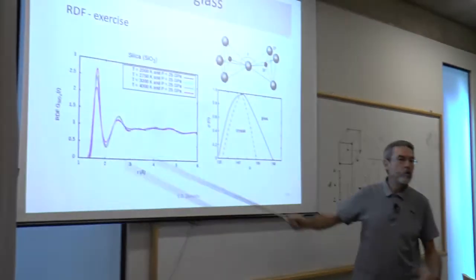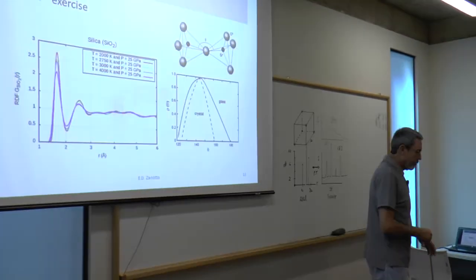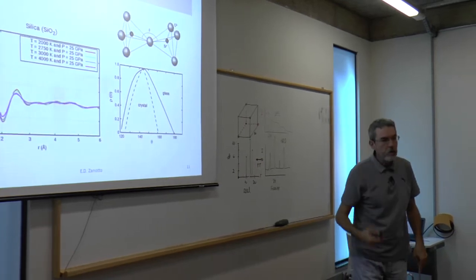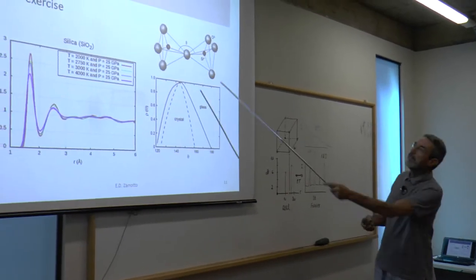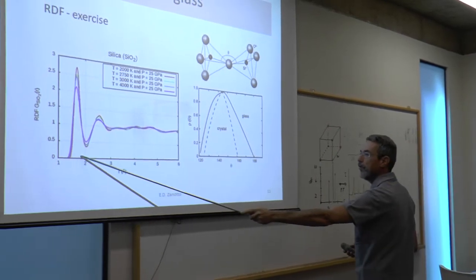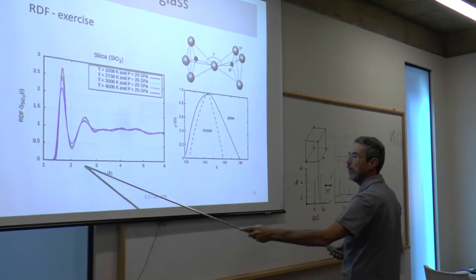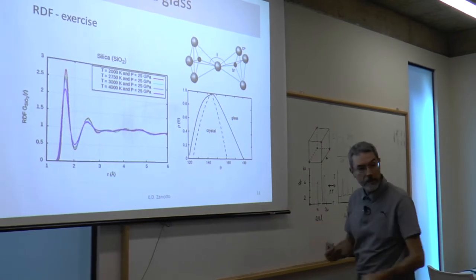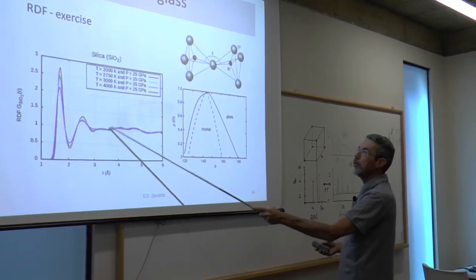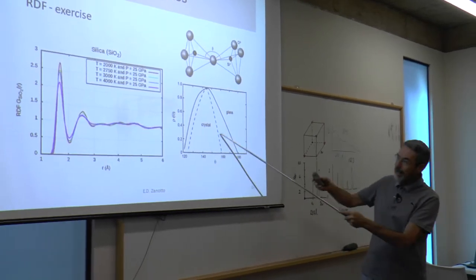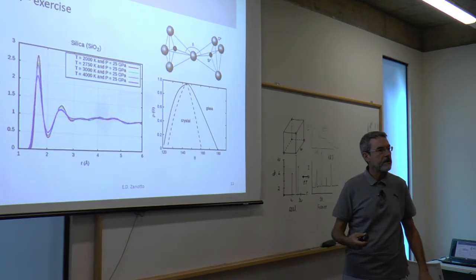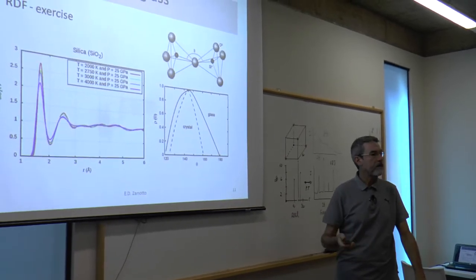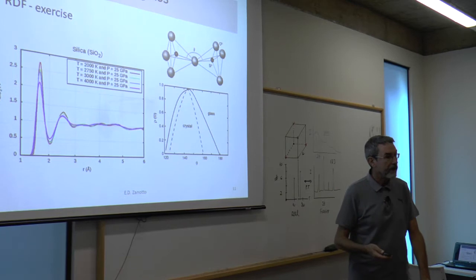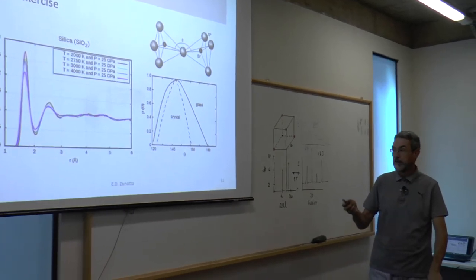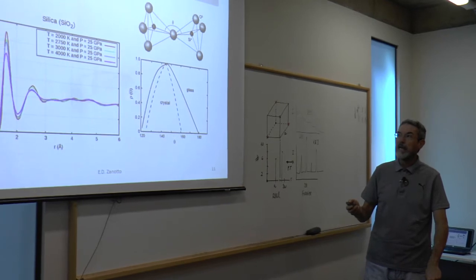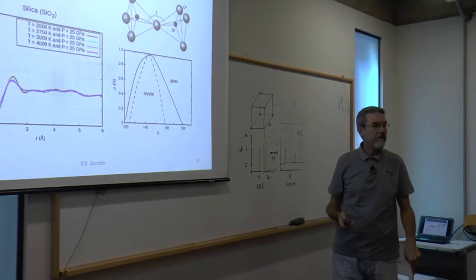This is how people do a lot of X-ray diffraction or neutron diffraction experiments to get information of this type here. What's the distance between the first neighbors? What's the coordination number? What is the distance between the second neighbors and the coordination number? And then the distribution of distances or angles of the paired neighbors, and so on. This is one method. There are many other methods to gather information about glass structure. But this is a powerful method that gives this type of information.